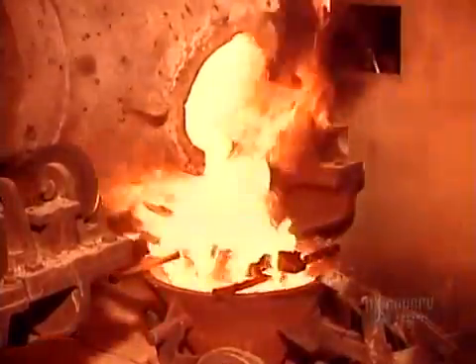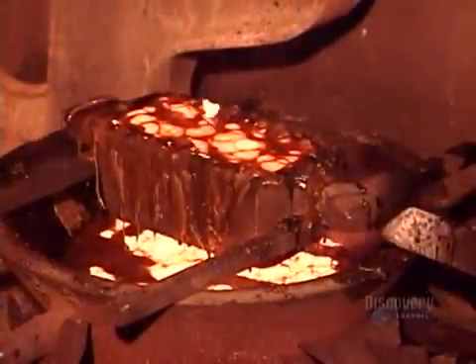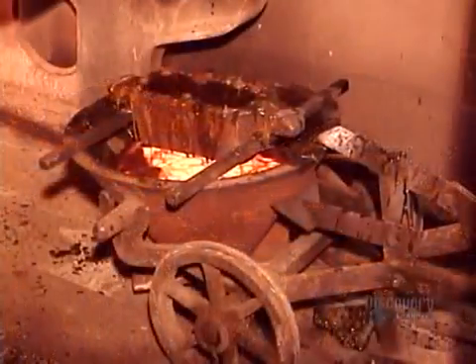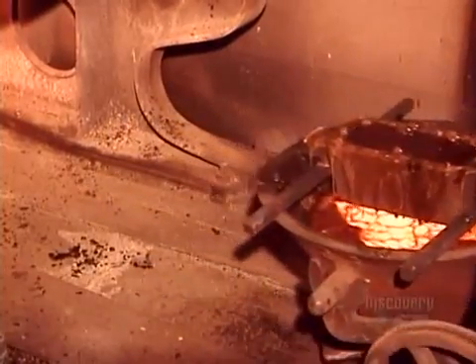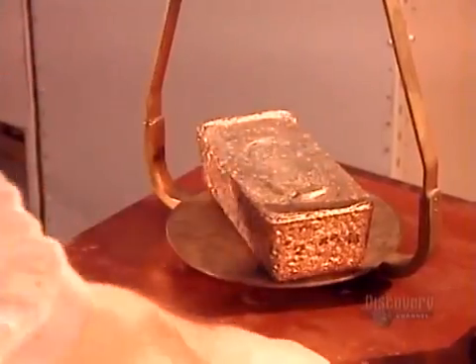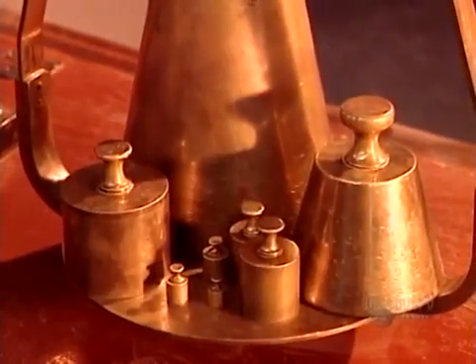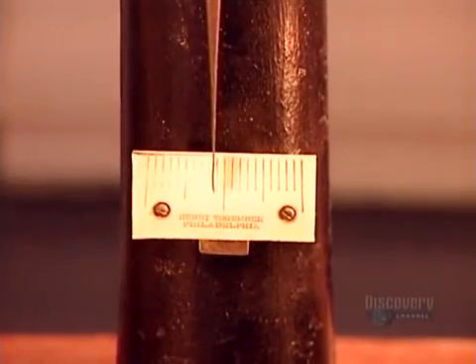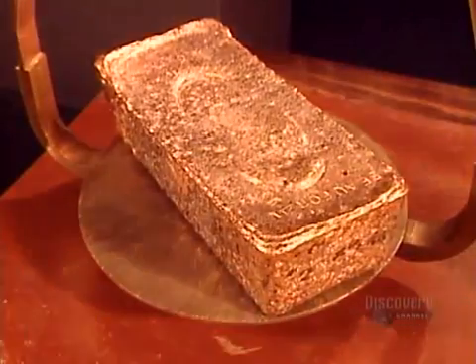By now, the gold has cooled slightly, so they reheat to 1600 degrees Celsius, then cast into bar-shaped molds. The gold takes about four minutes to solidify, then another hour to cool completely in a basin of cold water. They extract the gold bars from the molds and clean off any slag residue. Gold bars are also called ingots. At this stage the gold is 80% pure, and the Royal Canadian Mint will refine it to 99.9% — the international gold standard.